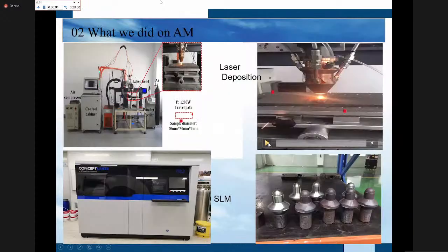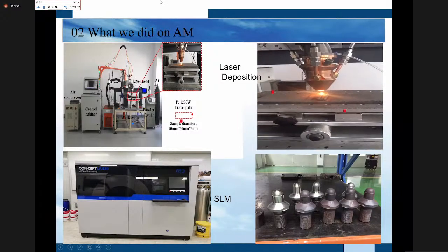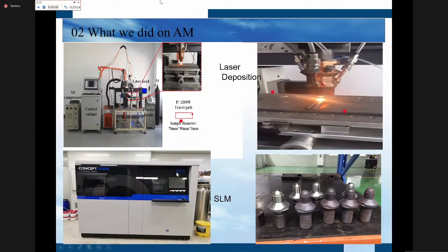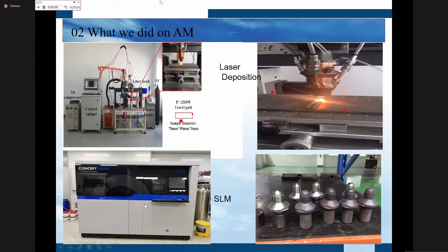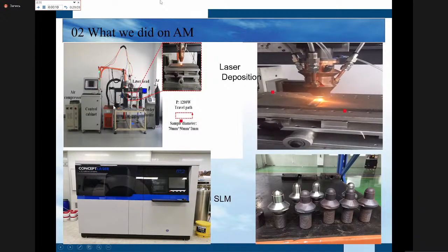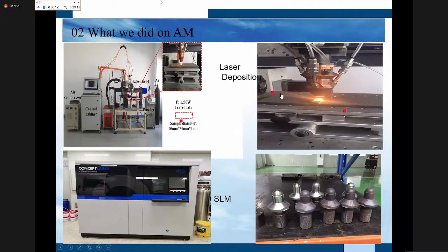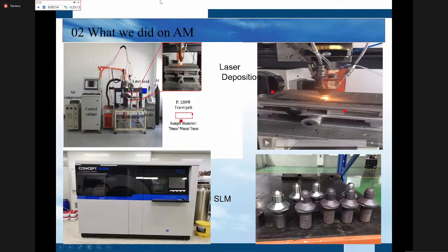Also, we did a laser direct. It's also some sample. We have SLM, but today we mainly introduce this. With this one we can print a sample, like we made some products for local companies on the surface coating. We also tried the HEA material. We get the hardness more than about 1,000 HV. So it has been applied in the local company.